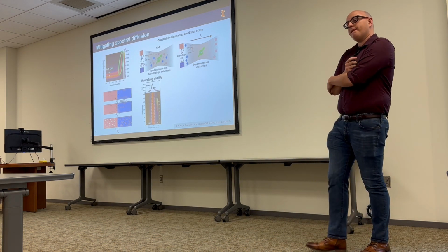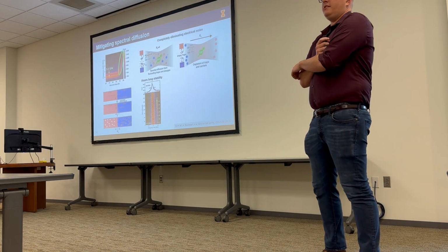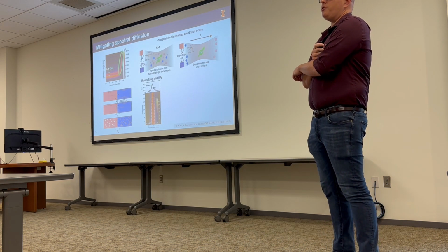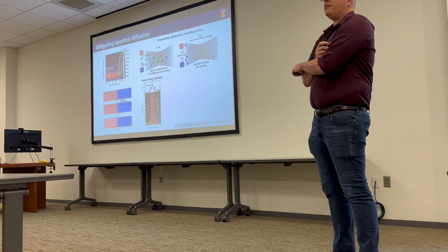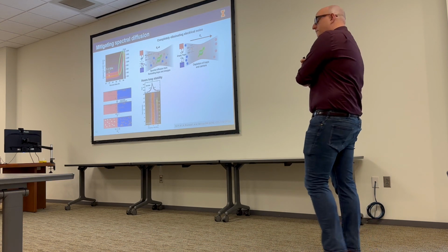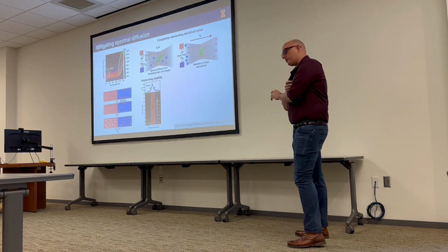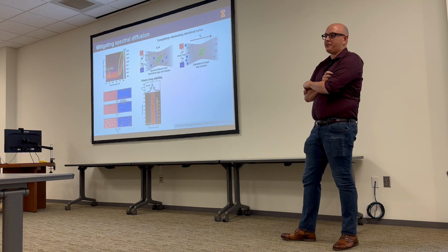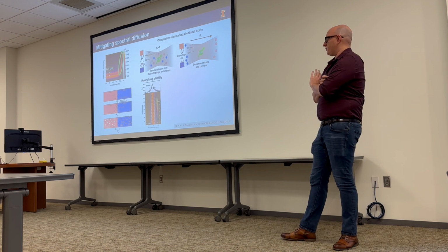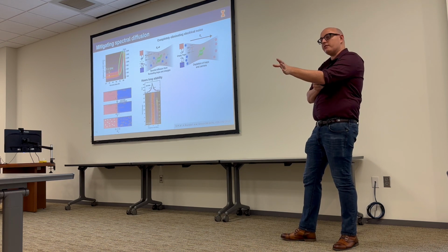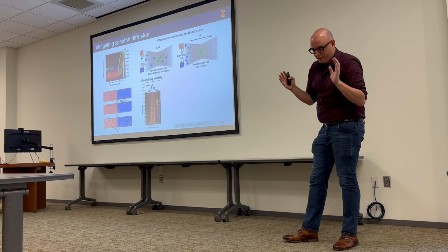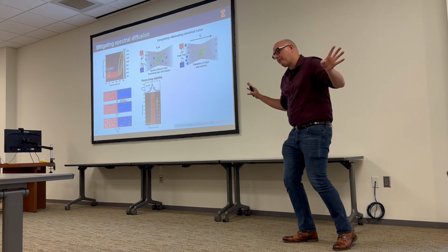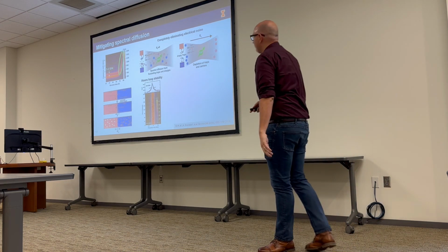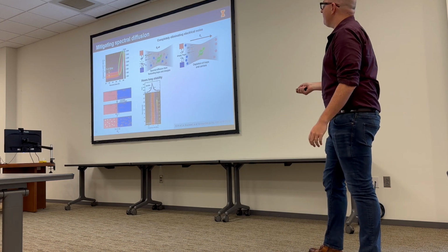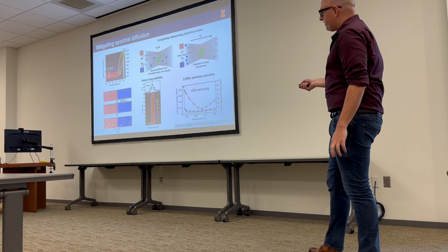This is in reverse bias. Yes. But you're above the breakdown? Below the breakdown. Yeah, the voltage is less than. Yep. And that's one of the benefits of having this be a high breakdown material. Yeah. So we were not actually limited by the breakdown of the semiconductor. We were just limited because we had a Keithley source that went to 200 volts. That was it. We could have gone more. Maybe we should have. But this thing narrows, which is great.